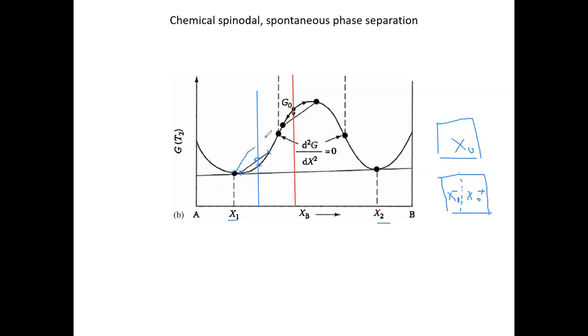But how about if I further increase the composition difference? Will this help? Well, we will see that for a wide range of composition differences, you keep on increasing free energy. You can only decrease free energy once one of the compositions goes far to this end. Only in this case do you start to lower the free energy. But to do that, you have to go over a very huge barrier from the thermodynamic point of view. This barrier is not due to any interface. This barrier is due to the nature of the free energy curve. So it's an intrinsic barrier, not like the interface barrier, which is due to the smallness of the nucleus. Even for this case, no matter how large your nucleus is, you have an intrinsic thermodynamic barrier that does not favor the kinetics of the transformation. So that's why we call this the bad composition. I hope this point is clear.